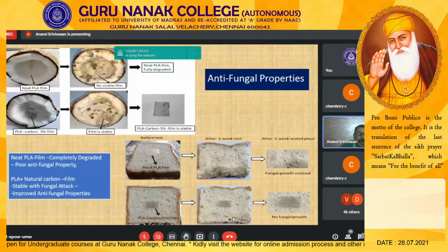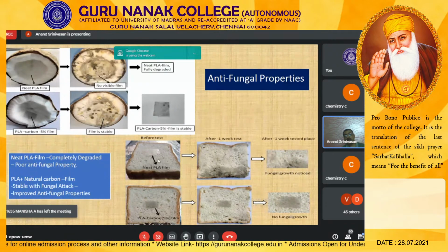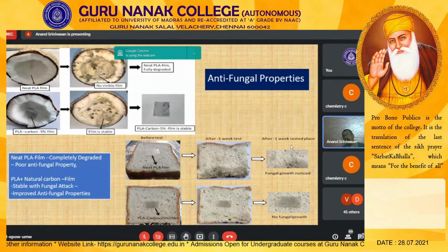Neat PLA did not have this antifungal property. Whereas when you reinforce natural carbon with the PLA, you can see the antifungal property is substantially improved. You can see this one is neat PLA film, which is completely vanished after 1 week testing time. Whereas you can see no fungal growth is observed on a PLA peanut shell carbon film.